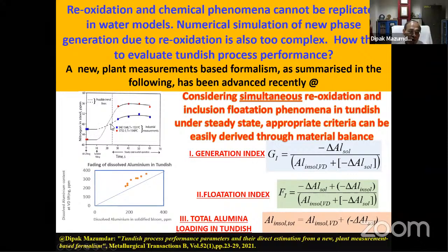So this is what I was talking about, that there's an air ingression taking place, because absorption of nitrogen essentially indicates that the melt has come in contact with the atmosphere. Along with nitrogen, varied amounts of oxygen will also get absorbed by the steel itself. And parallelly, as oxygen gets absorbed, we can see in this figure I have shown already, aluminum fading from the steel and alumina generation.